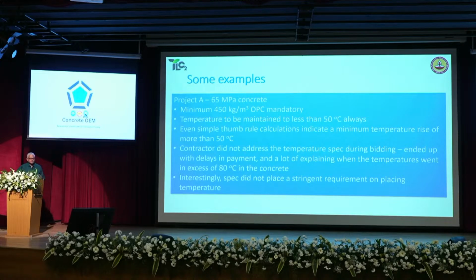So again, this is an issue with the specification. They have not really understood the impact of using high amounts of cement on the heat generation inside the concrete, right? And of course, in this case, the contractor also did not bring up this issue during bidding, which got them into trouble later because the concrete on site was actually exceeding 80 degrees Celsius, right? And they had to do a lot of explaining, the payments got delayed and so on and so forth. So again, a spec has to be carefully monitored, things have to be understood as to what is written in the spec, and we need to plan to ensure that such kind of issues don't really show up.